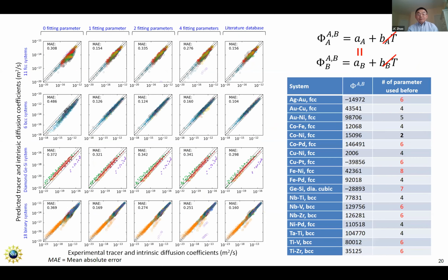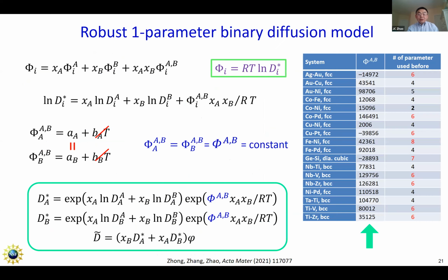So this is what we found. Basically, the B sub T term is completely unnecessary. And we found that you can use a single parameter to describe each binary system. If you insist on using 2 separate ones, I'm not going to cry over it, but please take out the B sub T term, so that you are not using more than 2 parameters per binary system.